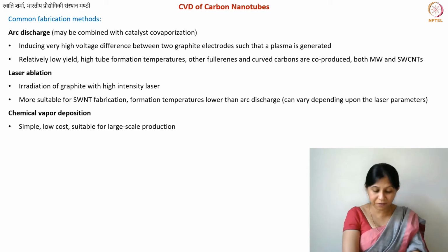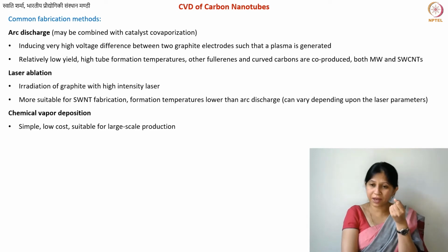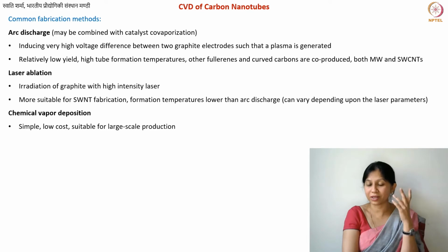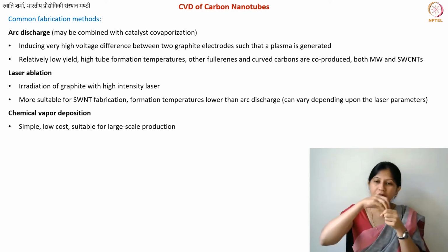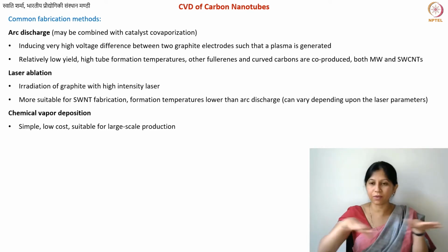The major difference is that now the catalyst is in the form of particles rather than films. If you give a very small surface for your carbon to deposit on, then it will deposit on top of each other rather than forming one single film. Even in the case of graphene, it's very hard to get one single film, right?